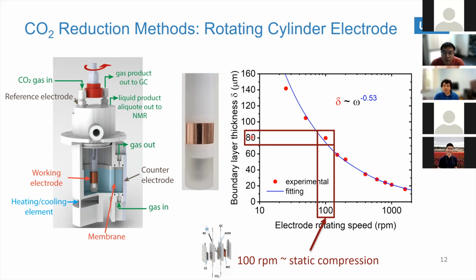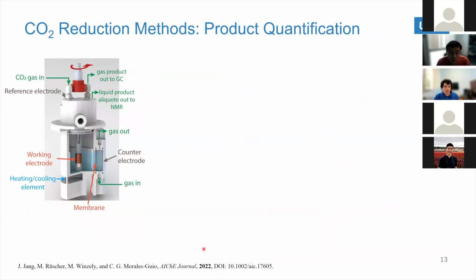If we compare that to state-of-the-art electrochemical cells that we use in our lab as well, those cells that are static, where the electrode is not moving, are equivalent to doing experiments at 100 RPM in our cell. So if we rotate at 100 RPM with this catalyst, we see exactly the same that we see in the static cell. But if we change the rotation speed, you start to see a lot of different trends in selectivity, and it just means that mass transport actually controls selectivity in CO2 reduction.